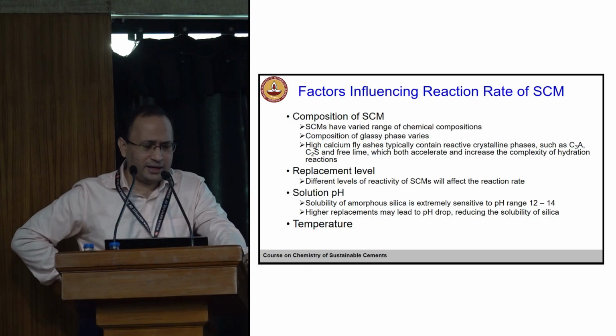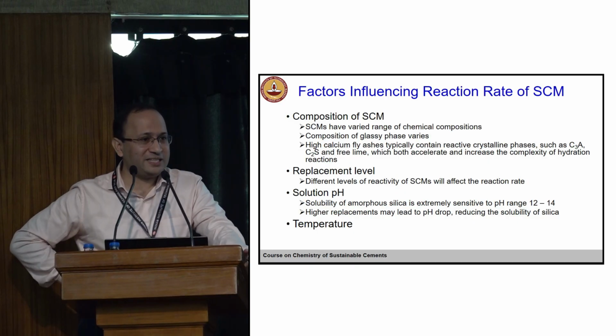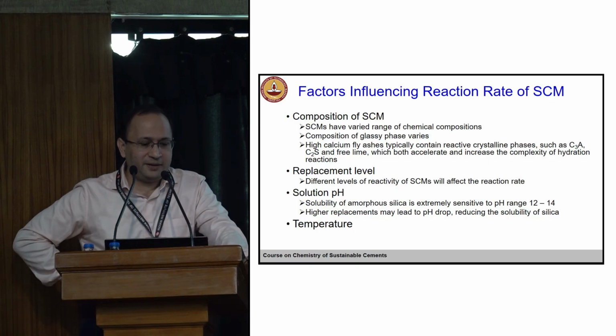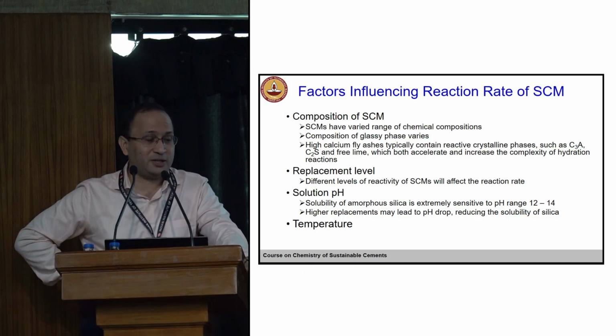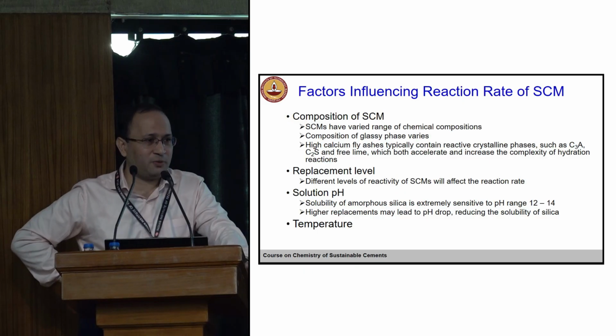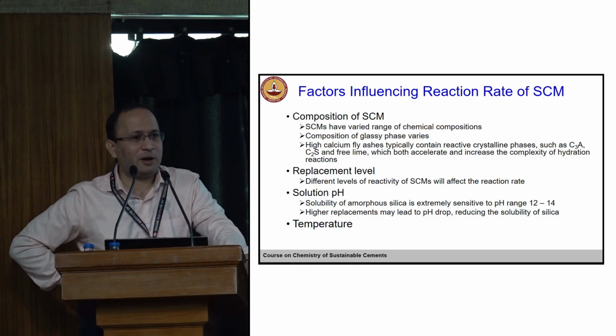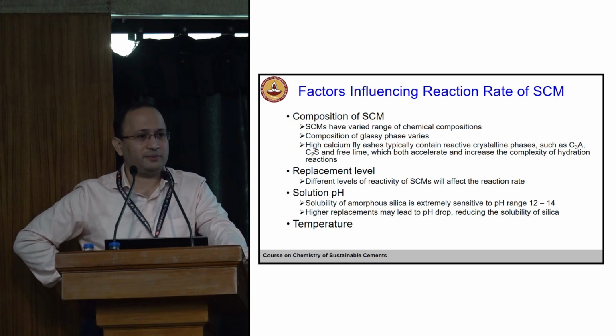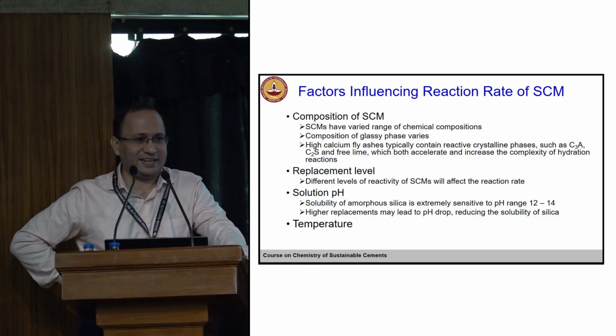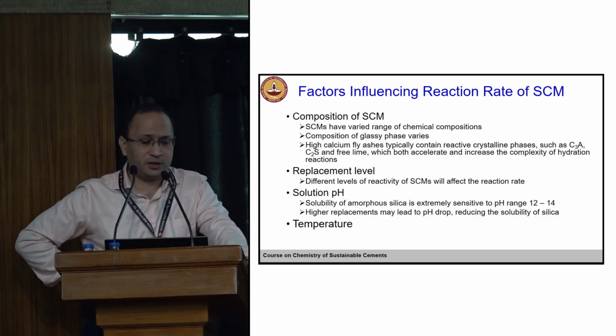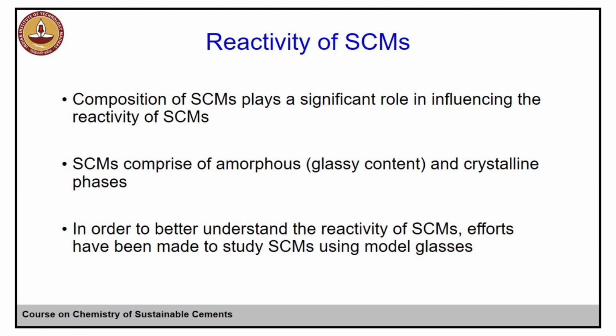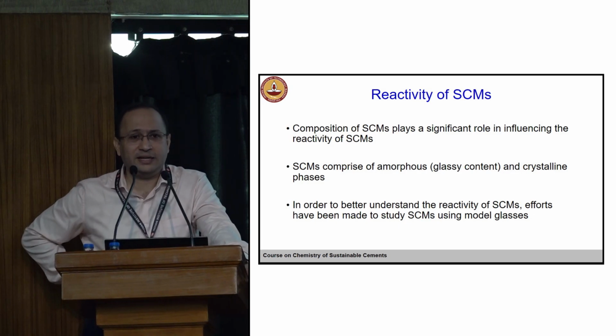And there's the replacement level, right? Depending on the degree of replacement level, we will have different extent of impact. pH also changes, right? pH will also affect the reactivity. Let's say an SCM in a higher pH environment will react more, for an example, compared to an environment of lower pH. And temperature, right? Temperature also will impact the reaction kinetics. So these are some of the important factors which will influence the reaction rate of SCMs. So that's why it becomes important to evaluate the reactivity of SCMs. So this is kind of a last section. It's very, very important. A lot of research is being done in this area.